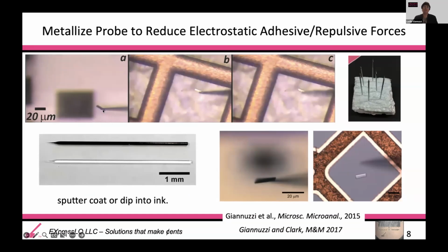We are not spearing it. We are not embedding the tip into the sample. We are just using the side surface area of the tip to touch the specimen. It clings to the probe via electrostatic forces, and then we can easily manipulate the specimen to, in this case,